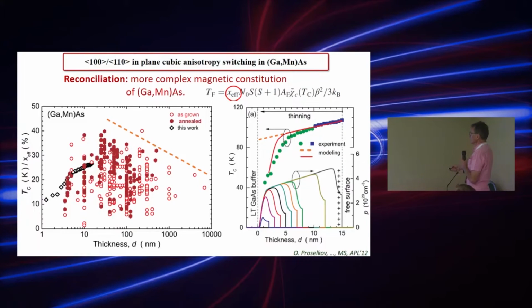As long as the layer is thick, these effects can be disregarded, and the Curie temperature is quite high. But now, as we thin the layer, and this is the result of an experiment, this is one sample that we thin in many steps, the Curie temperature is going down. The only way to understand it is that as the layer is getting thinner and thinner, more and more holes are taken away from this system.